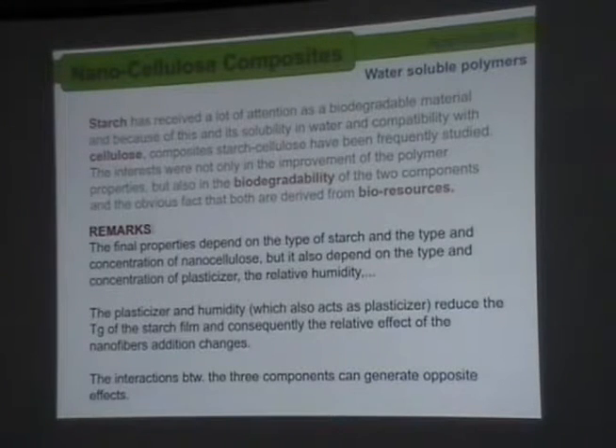If you prepare a film from starch alone, it is very rigid but breaks very easily, so you have to use it with a plasticizer, and you end up with what is called thermoplastic starch. But when you do that, you also increase the hygroscopicity — starch is already hygroscopic, and with the plasticizer it absorbs even more humidity. The plasticizer will reduce the Tg of the starch, making the difference between the modulus of the polymer and the modulus of the nanoparticles even higher, and any addition of these nanoparticles will be very sensitive in the final properties of the material.